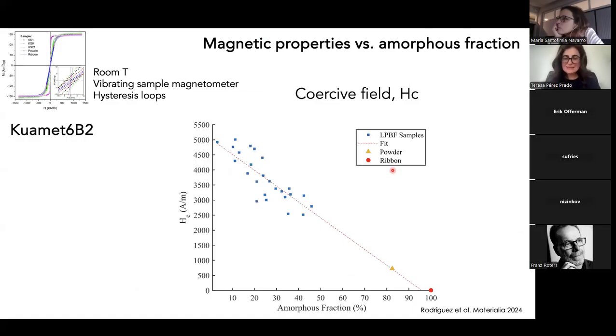But to finalize this first part of the talk, let us see how we are doing in terms of magnetic properties, because ultimately this is what we want. These were measured by our colleagues in Italy at room temperature, using the vibrating sample magnetometer technique. Here you see the hysteresis loop, and from there we measure the coercivity. This plot represents coercivity versus the amorphous fraction.